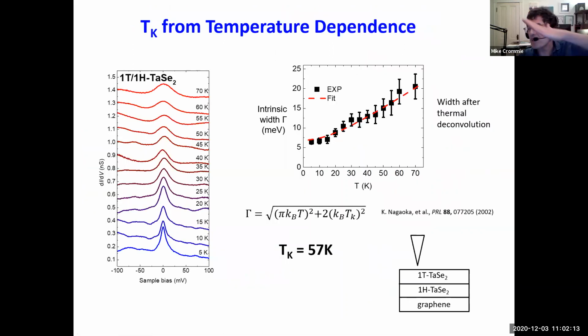Now, to test whether it's a Kondo resonance, we change the temperature, because Kondo resonances have a very characteristic temperature dependence. You expect the width to increase according to this characteristic equation that I showed down here. And that's been seen by our group a long time ago, and other groups have seen it as well in the last 20 years. And so we measured the width, and we can see that it widened, as you see here. And when we plot the width as a function of temperature for this Kondo resonance, we see that it follows very closely this expected Kondo behavior for a Kondo temperature of about 60 degrees Kelvin.